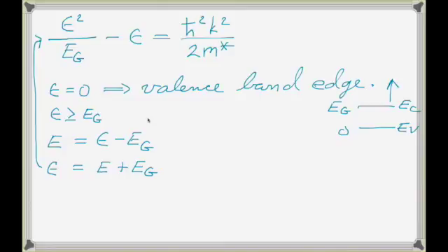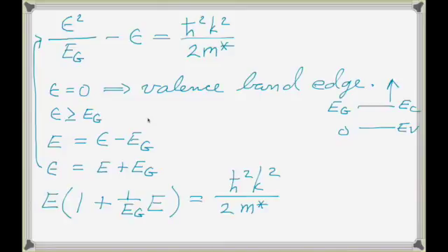And I finally get, and if we didn't have this term here, it would just be your normal parabolic dispersion. This is why this is called your non-parabolicity parameter, which I'll generalize in a moment. You can think of this as your correction term. If this term were 0, you would just have a parabolic dispersion.